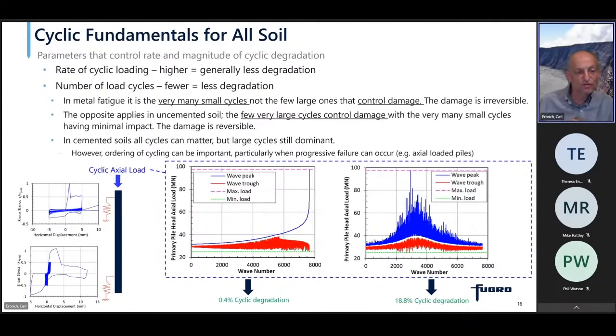Few more parameters: the rate of cyclic loading. The higher the rate of cyclic loading, because of that rate effect in most soils, we will generally get less degradation due to rate enhancement of the strength. And then, of course, number of load cycles. Fairly self-evidently, fewer cycles will lead to less degradation. But it is important, a couple of points here.